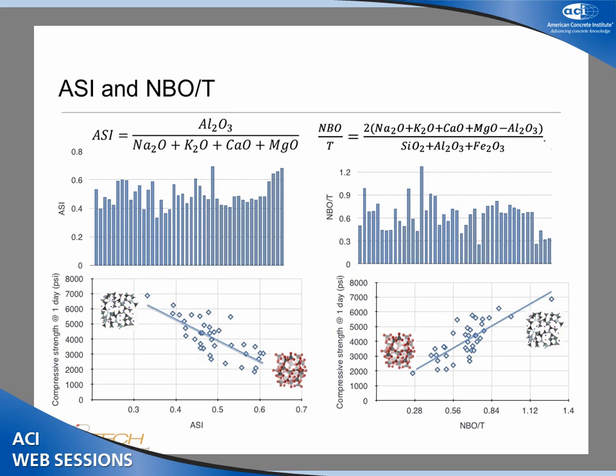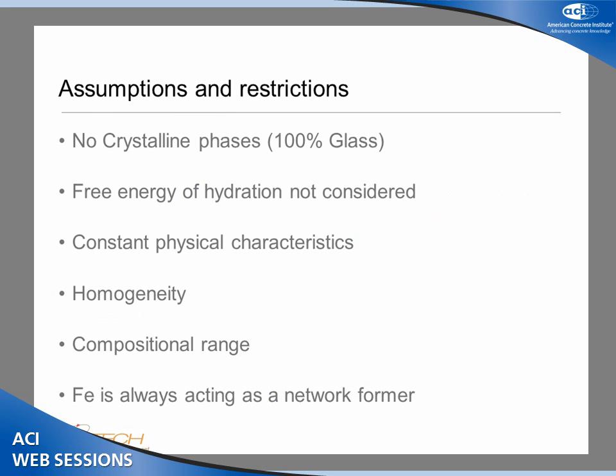And the same here for the non-bridging oxygens per tetrahedron. So as with any model, we have a number of assumptions and restrictions. Basically, the first one is that we assume that we have no crystalline phases. Obviously, that's not true. There are crystalline phases that are inert there. We also didn't consider the free energy of hydration. We considered that the physical characteristics are constants. We didn't take that into account. Obviously, there's variability there. We also consider that the material is homogeneous, and it's really not.